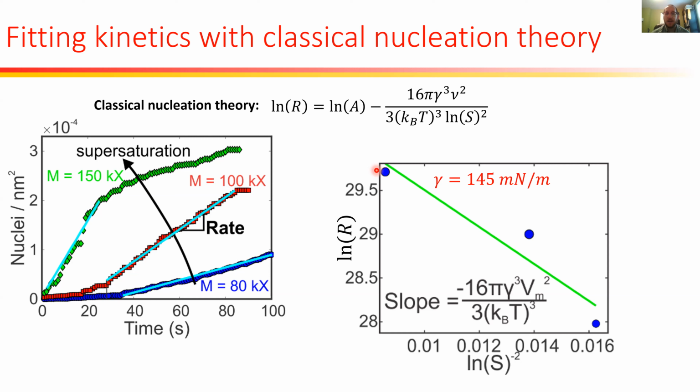There are people talking about the electron beam generating electric fields in our sample, which it can do. And the electric field will change the thermodynamics of the nucleation. You can add an extra term for the electric field to classical nucleation theory. The issue is the modeling is not accurate enough yet for us to know whether that's a significant effect.